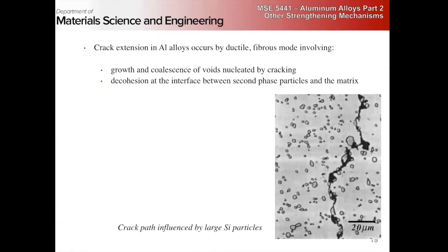So that means that we have a very low interfacial energy, that makes a very nice crack path, right? Because the crack doesn't have to do much work to separate the matrix from the particle, right? So if we have these intermetallics with low interfacial energies, they basically become beautiful paths for cracks to move along, right?